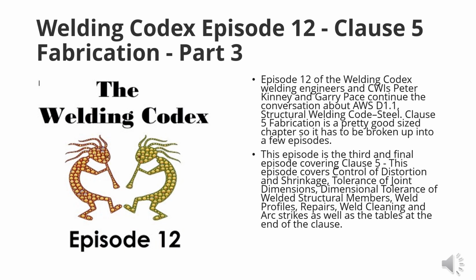and failures later on, because the problem here is that you take a piece of material and you heat it up and basically quench it. So you have this martensitic structure in this material, and it's just this place where it's going to fester and it can cause a crack, and depending on the cyclical nature of the loading situation, you can have all kinds of bad things going on. So that's why it's telling you, you've got to grind it smooth. The martensite isn't going to go very deep into the structure, so you just kind of scuff it off, take a little bit, take some meat off, and then have it checked with dye penetrant and visual, and have somebody, an authority, take a look at it and make sure everything's good to go.